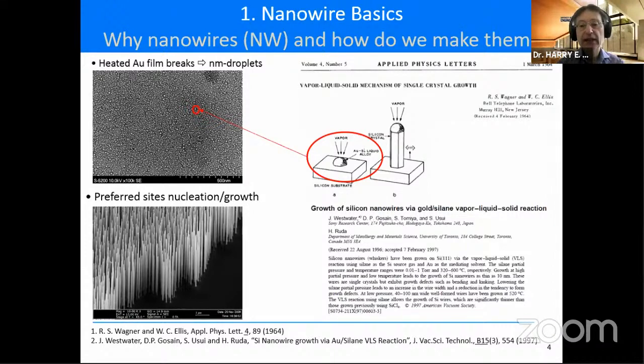So essentially, if you look in the red circle, you'll see there's a droplet of catalyst sitting on a substrate, and at the growth temperature that catalyst should be in the liquid phase, and it should have a sparing solubility for adatoms from the vapor phase. So the idea is atoms from the vapor, for example, say it was silicon atoms from the vapor, would impinge on the surface of this catalyst. Since it's sparingly soluble, the silicon in that, for example, gold catalyst, would be adsorbed, and we would build up a concentration until supersaturation of silicon in that gold was achieved, at which point they would want to precipitate out to relieve the supersaturation. And where would they do it? They'd do it at the low energy solid to liquid interface on the plane beneath. And that would carry up the liquid droplet like a candle, as shown in the right figure of their paper.